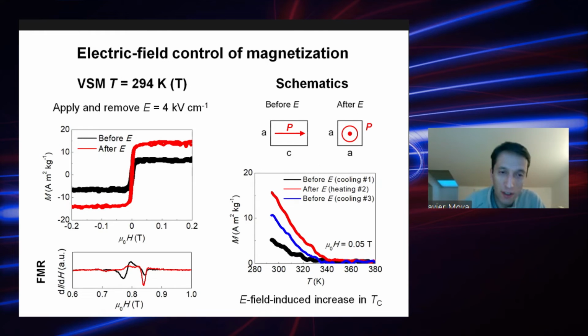Then what we did is we focus on the room temperature phase. Because the room temperature phase is interesting because the film is closer to the Curie point, so you may expect to change the magnetic properties more dramatically. And also interestingly, the strain changes are very large, associated with the rotation of the polarization with the diagonal phase. So what we did here is we measure again magnetization as a function of field before and after electric field. And you can see again that there is a very big change in magnetization now in this film, which is good because this is going to give us a very large magnetoelectric effect.